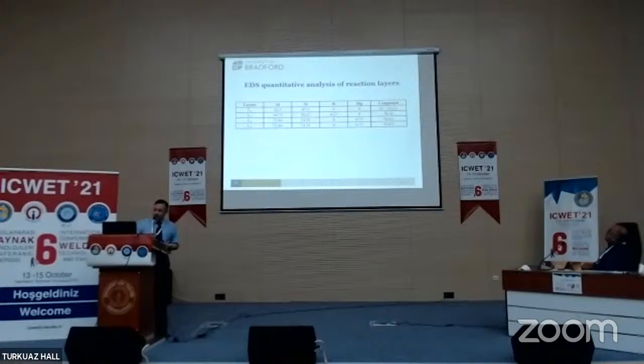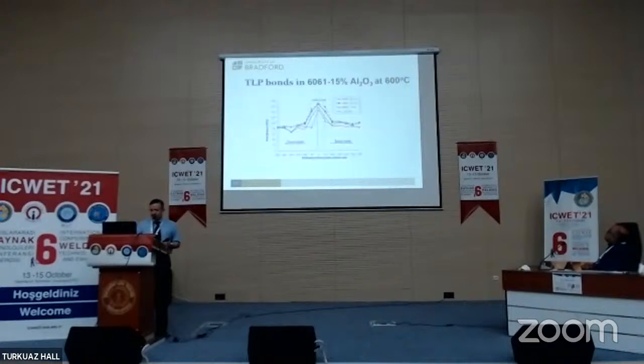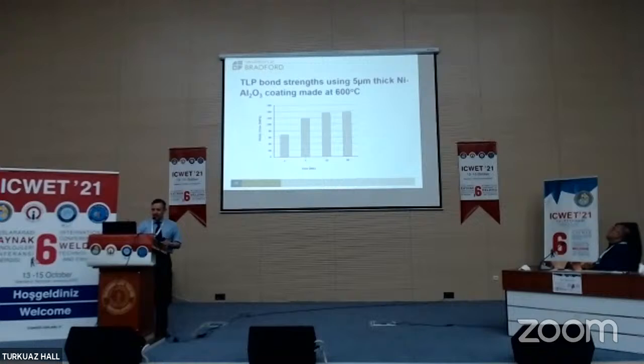Here what we find is that we've also got the detection of alumina present within the joint region. So we were able to detect both the nickel and alumina. Further away in the different reactions, we find different nickel aluminide intermetallics forming. So you can use these particles and they do have an effect. And as the bonding time increases, the hardness begins to decrease as well. And what we find is that the shear strength as a function of time is also better for these joints.